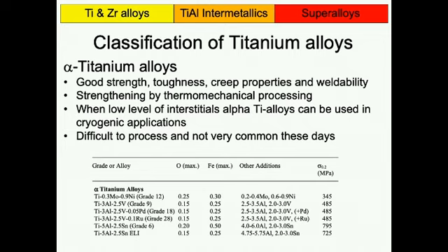Remember when we discussed diffusion rates? Creep is very much a diffusion controlled process. So if you have a crystal structure which is closely packed and has low diffusion rate, you end up with better creep properties. And by having some noticeable amount of beta phase in the material, you might actually deteriorate the creep properties of such a material.